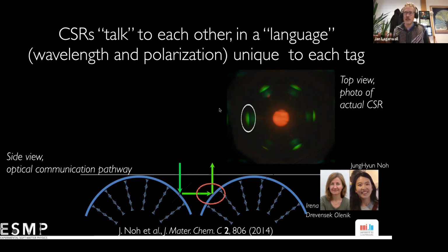But this is Bragg reflection we are dealing with. So when you have retroreflection, that's 0 reflection angle. But here it's 45-degree reflection angle. So that means you get a blue shift, and that's why for the same shell you get red in the back reflection, but you get green in the side reflection in this communication pattern.